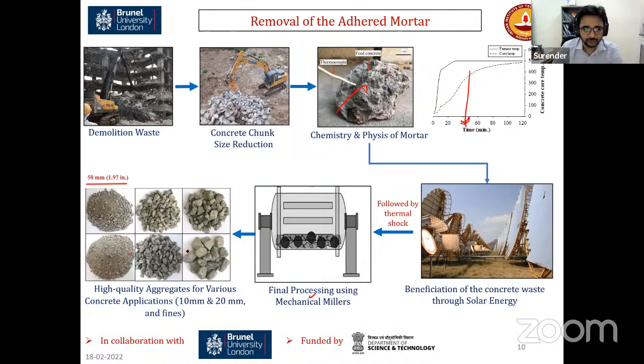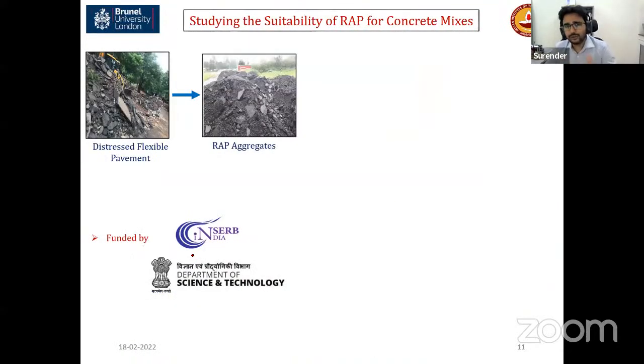And you can see Rohit has also shown this figure. In these aggregates, you can see a lot of adhered mortar, but in the case of the 20 mm aggregates, we were able to remove mostly all the adhered mortar content, and the quality of the aggregates was on par with the pristine aggregates. Also, we are working on the reclaimed asphalt pavement aggregate.